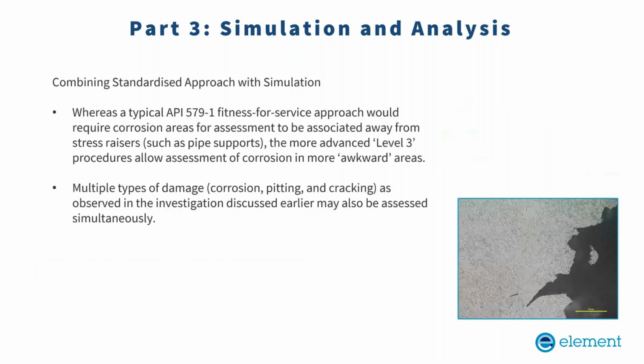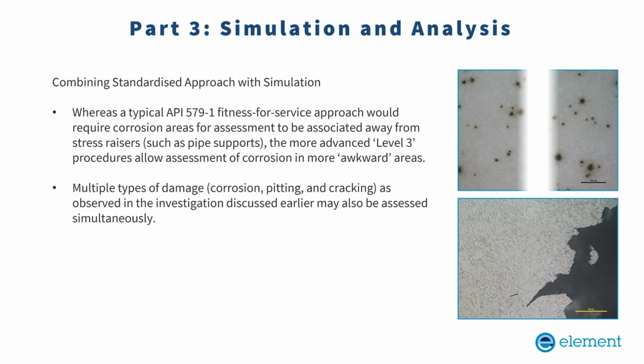The advanced level 3 analysis, per 579 part 1, was conducted, which is actually recommended by this standard for such situations. This type of analysis allows us to simulate the actual condition of the pipe with multiple damage, and by this analysis we were able to find out what is the impact of this crack present in the material, what will be the impact on the remnant life of this pipe, of these structures.